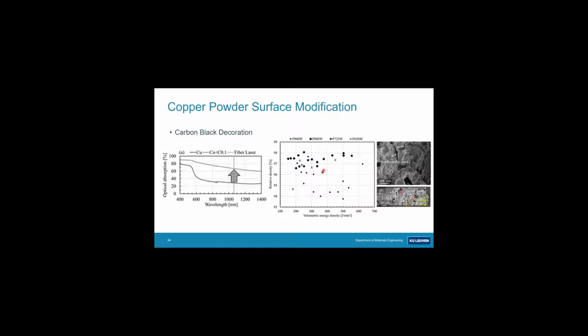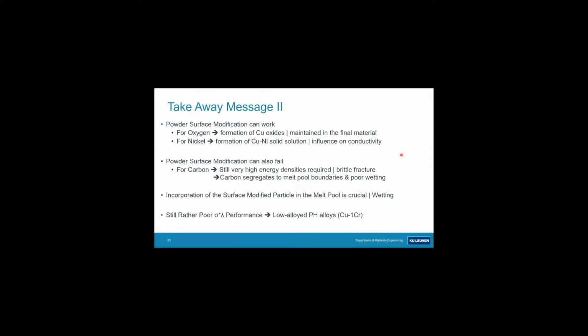From the moment that these surface-modified powder particles were sucked into the liquid melt pool, they could still play their role as absorption-enhancing medium, which was not the case with carbon particles, which immediately segregated and did not contribute to any enhanced absorption. So that's takeaway message number 2. It seems to work for some surface modifications, but for example, for pure carbon, it did not work. And so there are other effects playing besides the pure optical absorption in the powder bed.